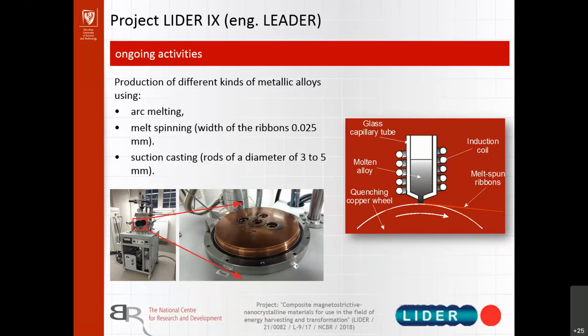So in this way, we are able to obtain metallic alloys, but in the form of metallic glasses. I'm sure that you know that glasses have an amorphous structure, so there are no crystalline structures. So this is how we are able to obtain metallic glasses. Our material is supposed to have an amorphous structure, and from the amorphous structure, we are able to change it to a nanocrystalline structure with specific heat treatment.